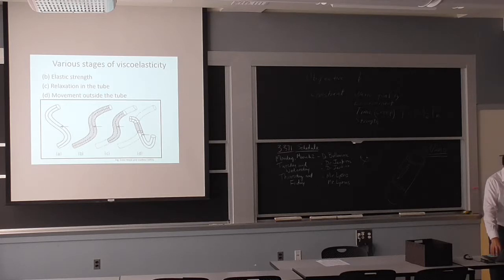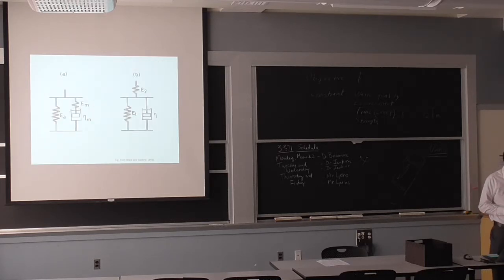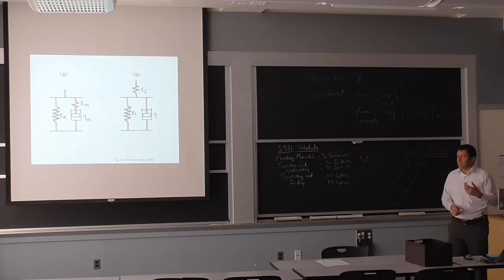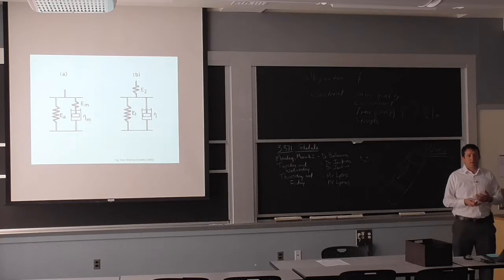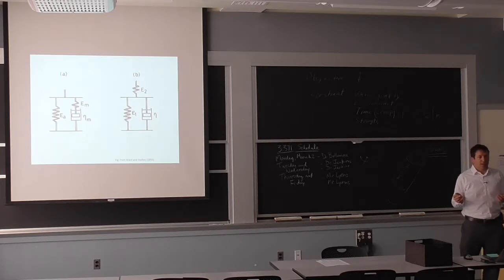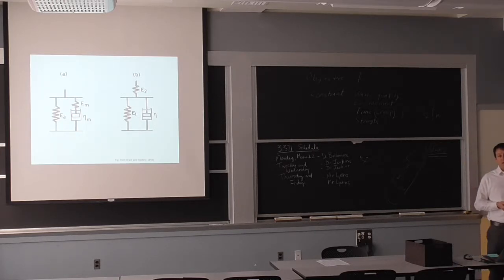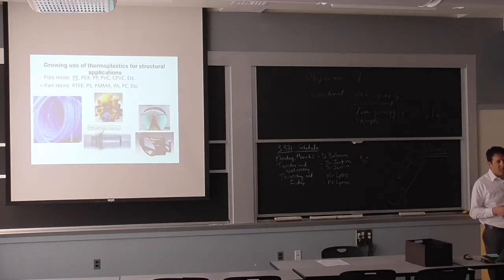So I find a lot of limitation for this, because most of the time these models assume that you're linear elastic, viscoelastic. What does that mean? If I take a certain stress, say I'm putting 10 megapascal of load on the polymer, and it's deforming by this much over time, I'm saying if I put 20, it's just going to be twice the amount. Well, in reality, most of the time as you increase the demand, you get a lot more deformation. And that's why it's viscoelastic, but it is non-linear for most cases. It'd be close to linear for polyethylene sometimes when you're very, very close to not moving. But that in itself doesn't mean much.